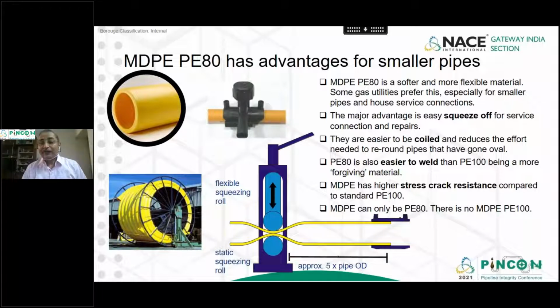The major advantage is easy squeeze-off for service connections and repairs. MDPE pipes are easy to coil and reduce the effort of re-rounding pipes that have gone oval. PE80 is also easier to weld than PE100, being a more forgiving material. And another major advantage is MDPE has very high stress crack resistance compared to a standard PE100 HDPE material.